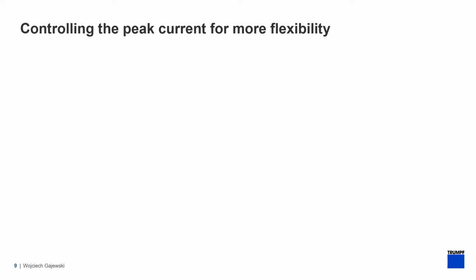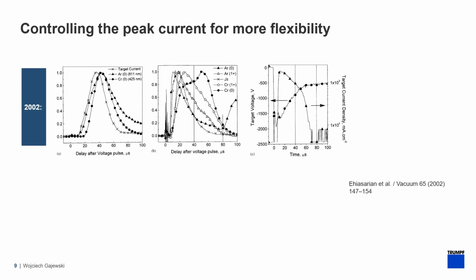In order to define next steps in HIPIMS power supplies development, it was important to look not only at the coating properties, but also to include the plasma properties as well as the deposition process properties. And it was shown already in 2002 that the shape of the voltage and current pulse influenced the optical properties of the plasma. It also influences the dynamics of the ions arriving at the substrate.